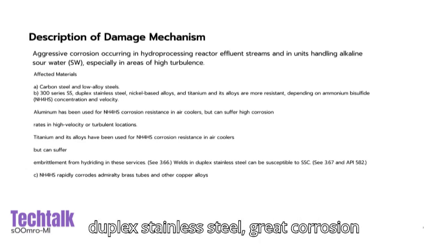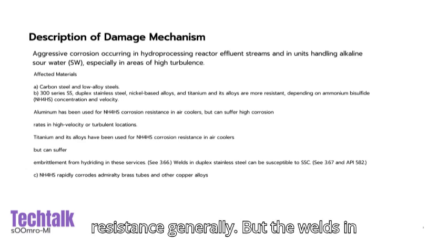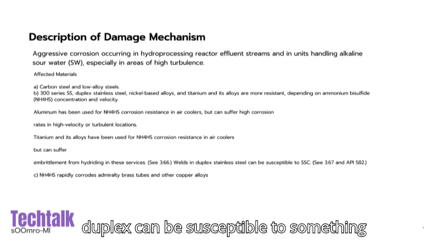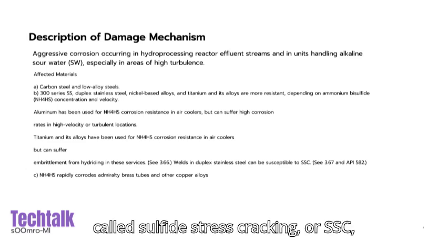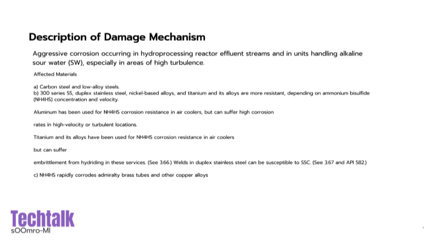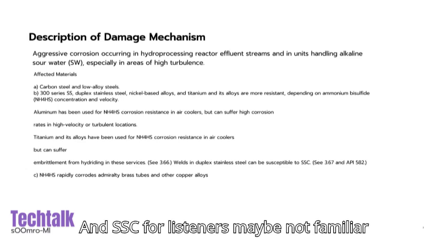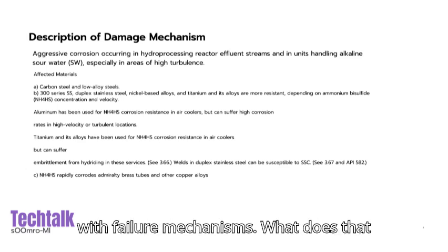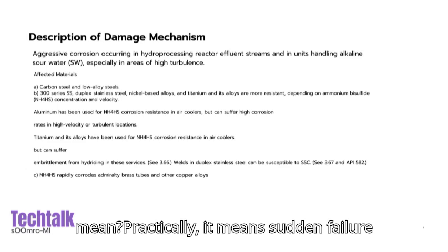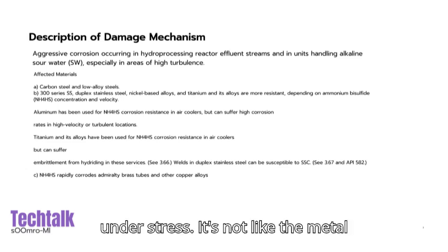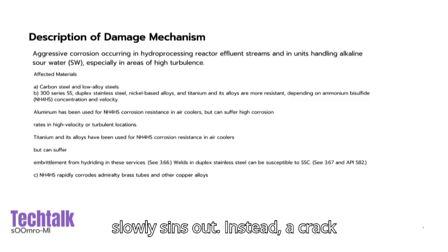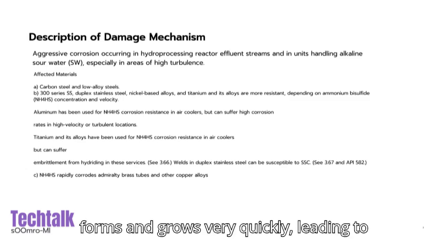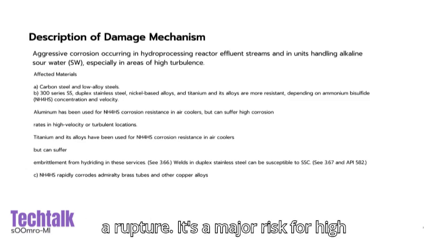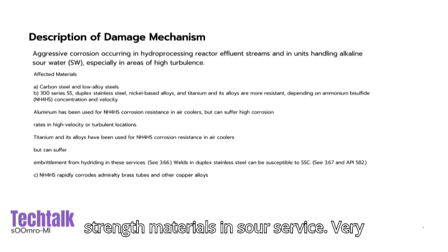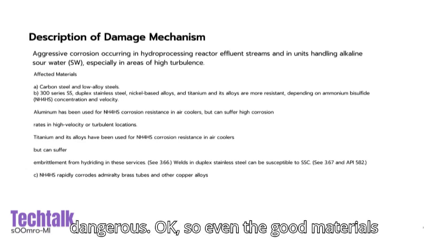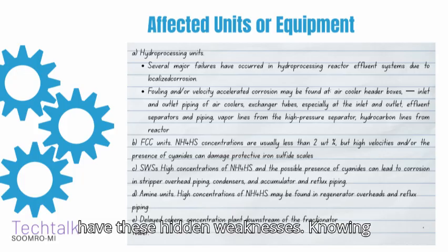Or think about duplex stainless steel. Great corrosion resistance generally. But the welds in duplex can be susceptible to something called sulfide stress cracking, or SSC, especially if not heat treated properly. And SSC, for listeners maybe not familiar with failure mechanisms, what does that mean practically? It means sudden failure under stress. It's not like the metal slowly thins out. Instead, a crack forms and grows very quickly, leading to a rupture. It's a major risk for high-strength materials in sour service. Very dangerous. Okay, so even the good materials have these hidden weaknesses.